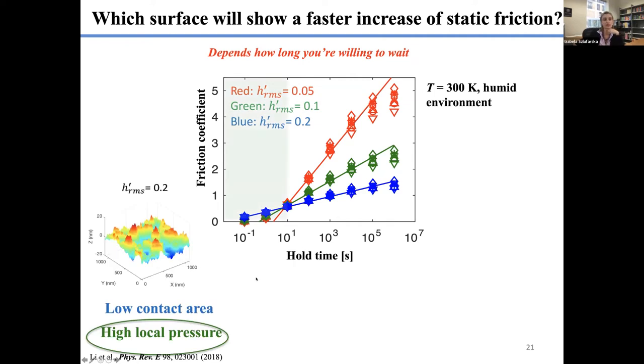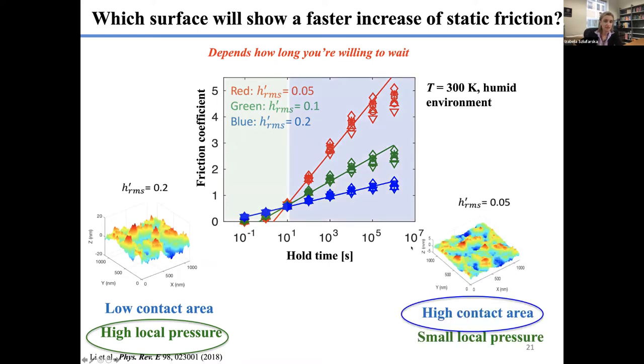So if you just put them together at first, it turns out that the rough contact, the blue one, is going to age really fast. The reason is because the contact area is not large, but has very high pressure. And this pressure is just going to catalyze chemical reactions really fast. But if you wait longer, over a longer period of time, these high pressure points are used up. And then what matters over a long time is how much contact area we have. And that's why you see in the long term, the smoother surface with a higher contact area is going to have more chemical aging.